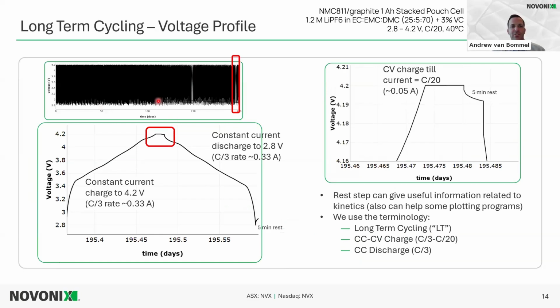So now after that formation step, I'll talk about long-term cycling. Here's a messy voltage profile showing voltage versus time. So much messier because each one of these is a charge and then a discharge. So it's just all pushed together in this graph here. If we zoom in on one charge-discharge cycle here, just to go over some of our standard testing for long-term cycling, it's done at a constant rate of charge, a constant rate of discharge. So this is C/3 rate for a 1 amp hour cell. That's about a third of an amp.